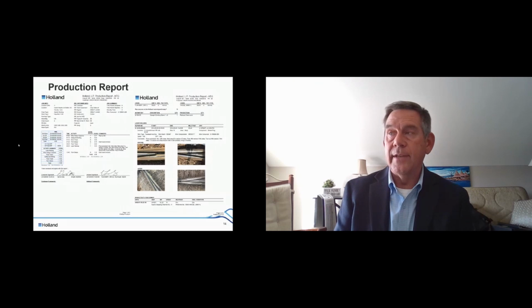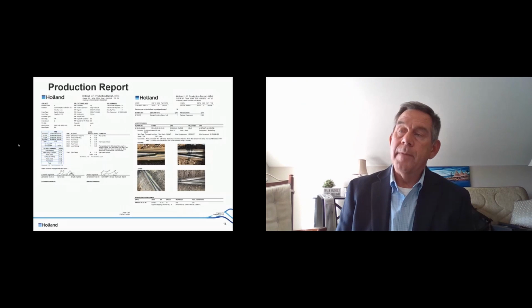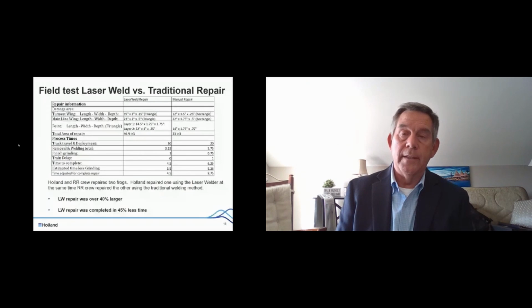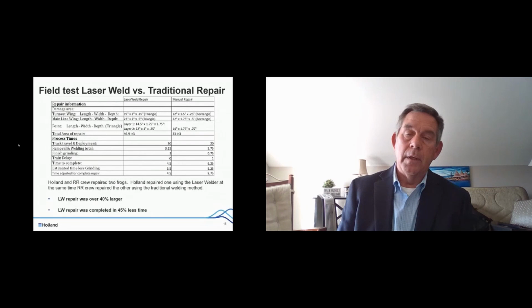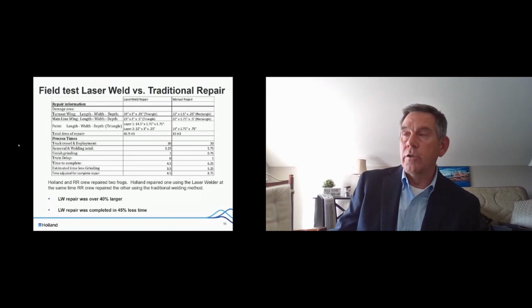Holland also did a side-by-side test in the field with a railroad that repaired a frog on the same line. They were both done at the same time. One was using the standard MIG welding process. The other was the laser weld, and tried to create exactly the same repair. However, because the laser weld process is so much faster, we were able to repair an area that was 40% larger, and yet it was done in 45% less time than the traditional repair process. So it clearly demonstrated that the repair can be done faster, and a much larger and more complete repair can be done, which is also going to lead to longer life.